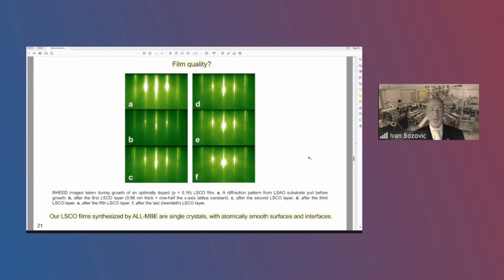A characterization tool that we use every day in situ and in real time is electron diffraction. What it shows is that the film is single crystal, no grains, no grain boundaries, atomically smooth, uniform, and epitaxially anchored to the substrate.